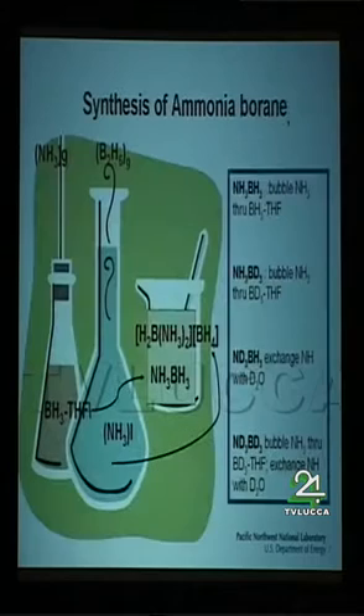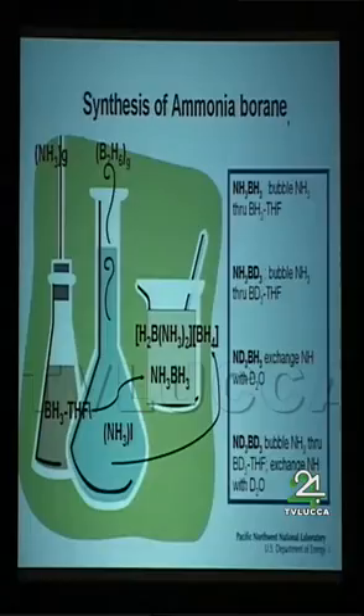So here's my cartoon slide. Here's a physical organic chemist's approach to synthesis. The ammonia borane itself could be synthesized quite easily. There's other ways to do it, but if we want to get the deuterium incorporation in here, the simplest way, you can bubble ammonia through a BH3 etherate solution, and then just excess ammonia, remove the solvent when you're done, and you have ammonia borane. A very clean, pure way of making it.